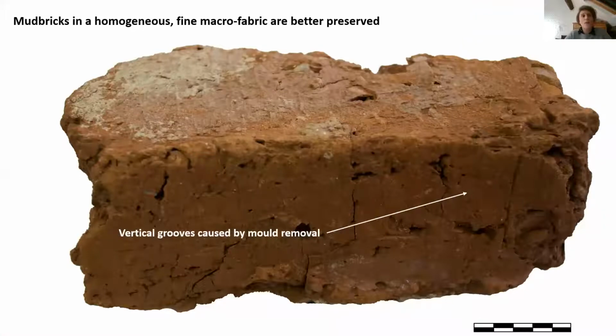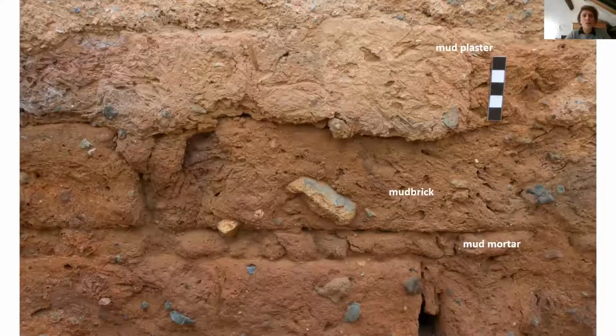We noticed that the mudbricks with a fine macrofabric erode less easily, and in some cases, minute details related to their fabrication are still visible on their surface. You have here the example where fine vertical grooves left by the wooden mold when it was removed from the mudbrick are still visible. So it is noticeable that the macroscopic composition of the mudbricks strongly affected their performance. The finer, the better. The coating of mudbrick walls with mud plaster protected them from erosion, humidity, and parasites.